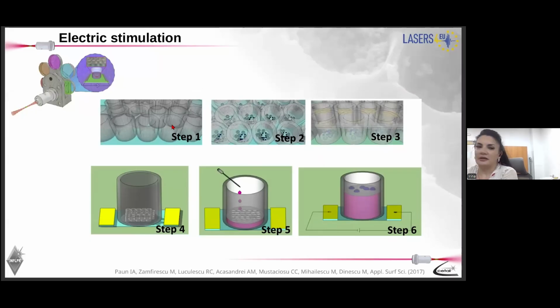We first fabricated the microreservoirs by laser printing. We filled them with polypyrrole, which is an electrically conductive polymer, and dexamethasone. We sealed them with PLGA, which is a biodegradable polymer. We did this to prevent the passive diffusion of the drug. Then we placed this between electrodes. We seeded osteoblast-like cells on these structures, and then we tried to release the drug by externally applied electrical stimuli.